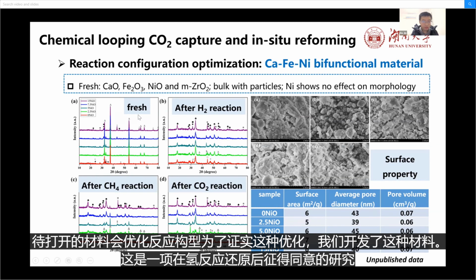This is the XRD for the as-synthesized material, after hydrogen reaction, after methane reaction and CO2 reduction. From this calculation, you will see for this fresh material, it has calcium oxide, iron oxide, and nickel oxide, and there's monoclinic zirconium oxide. After hydrogen reduction, there's iron and nickel. And after methane reaction, there's also nickel, but the iron oxide maybe is FeO. And after CO2 capture, the iron oxide can be recovered. For this SEM, with increasing nickel oxide, you will see there's some fine particles. And for the texture property, nickel has no effect on the surface area.